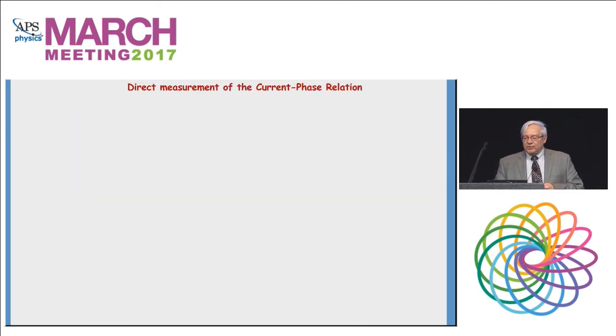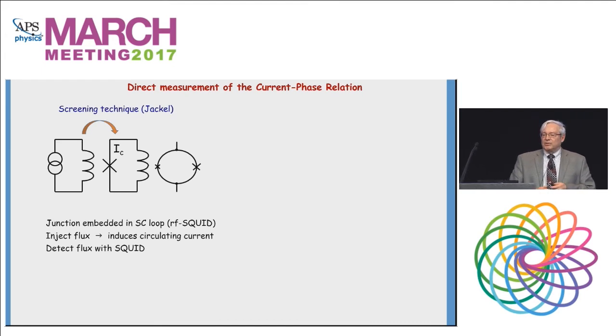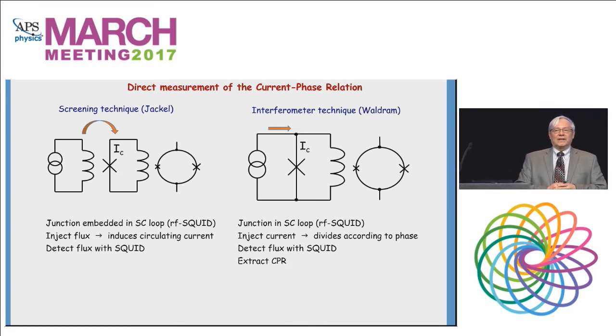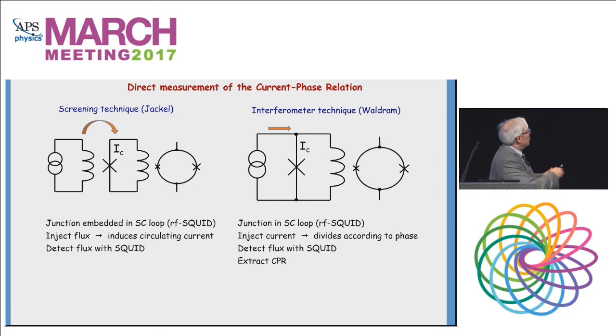So there's lots of ways to do this. The technique that Cam has used was one developed originally by Larry Jackel and the Bell Labs people. This is where you inject a flux and look at the screening currents to detect that with a SQUID. The technique I learned about was when I was at Cambridge with John Waldram. It's sort of the current injection version of this. You put a current into the junction, divide it through an inductor. Basically, the current divides according to the phase, and by reading the current in the inductor, you can subtract that out and extract the current phase relation.